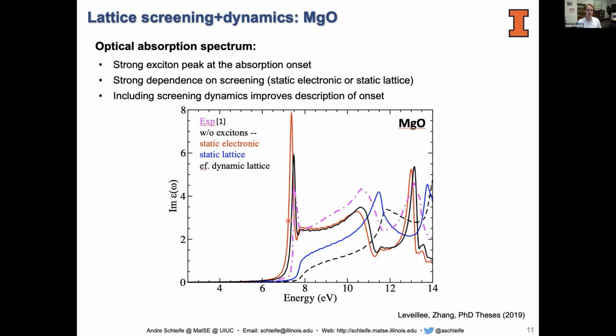And then what Josh and Zhao did, which is unfortunately not published in a journal yet, we're working on that, it's in their PhD thesis, is that if we implement a dynamical screening and compute the optical spectrum, we see an improvement in terms of the peak position and the peak height. So it improves the agreement with the experiment here at the onset. We also see effects at higher energies that seem to push it in the right direction compared to experiment.